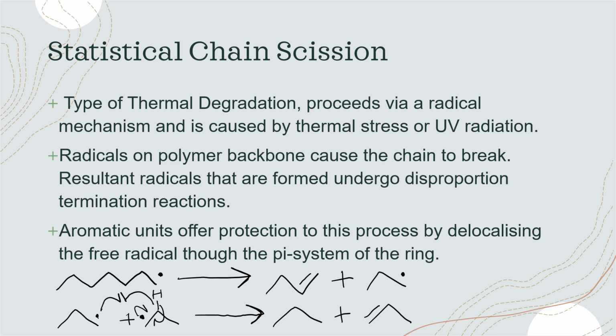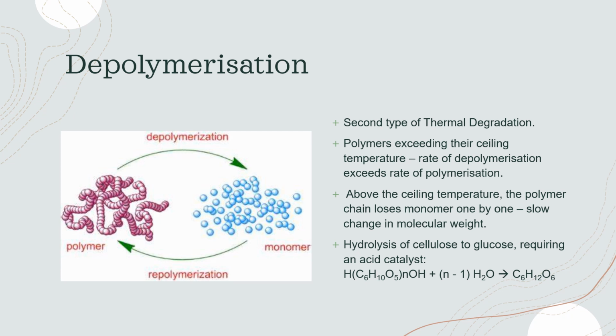At the bottom of the slide is a typical example of an aliphatic polymer chain undergoing statistical chain scission. The second type of thermal degradation mechanism is depolymerization. This process occurs when polymers are exposed to temperatures above their ceiling temperature and the depolymerization rate is greater than that of polymerization. This event effectively inhibits the formation of polymer, as monomer units are lost greater than monomer units forming polymer chains. Depolymerization, unlike statistical chain scission, occurs slowly, as the polymer chain only loses monomer from the end of the chain one by one.